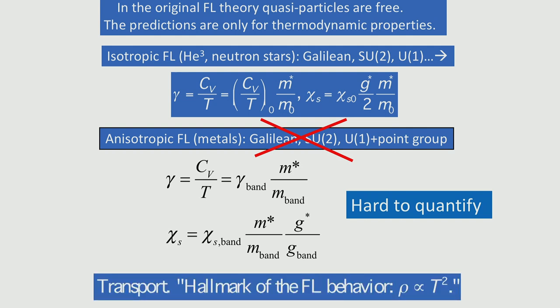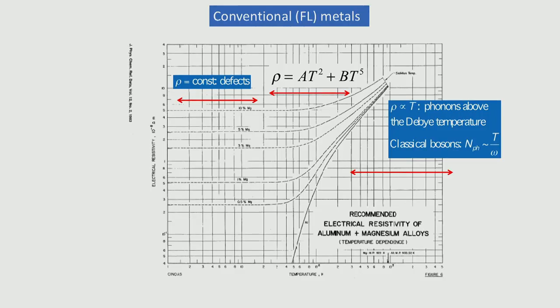In this way, the predictions become less quantitative compared to helium-3, and this is why people turn to transport. Because in order to have transport, you need to bring in some residual interaction between quasiparticles - you need to take into account the scattering. What is usually considered a hallmark of Fermi liquid behavior is that the T² dependence of the scattering rate is automatically translated into a T² dependence of the resistivity. And this is one of the pitfalls I'm going to walk over.